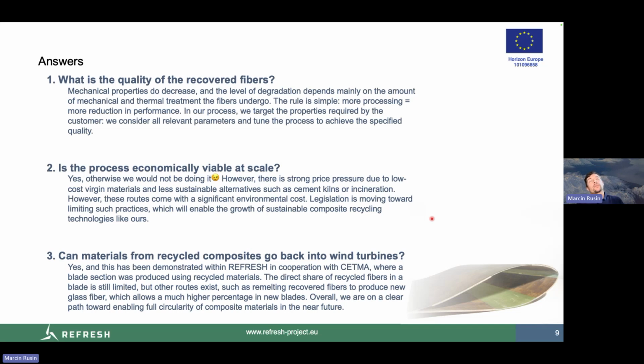Yes, the quality of the fibers is a bit lower than the virgin fibers, and that's because we are processing the fibers first mechanically, then thermally, and then mechanically again. So there is some degradation of the material properties.